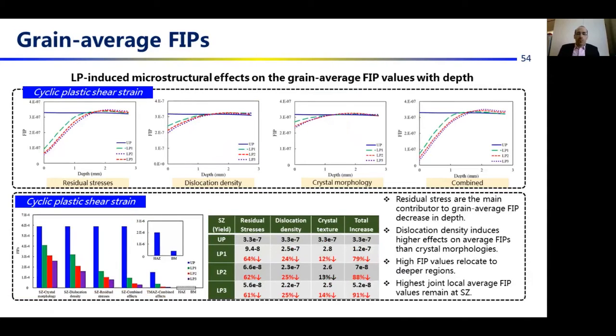From the grain average FIPs, we have still the residual stresses as the main contributor to grain average FIP decrease, and then dislocation density induces higher effects from the magnitude and depth than the crystal morphology effect, and the high FIP values relocate to the deeper surface regions where the fatigue failure is more likely to happen after laser peening, and still the highest joint local average FIP remain at SZ area after laser peening, which shows that fatigue location is less likely to change after laser peening.